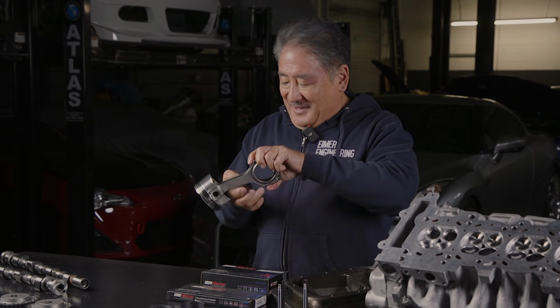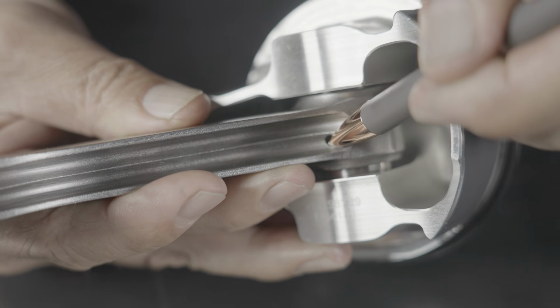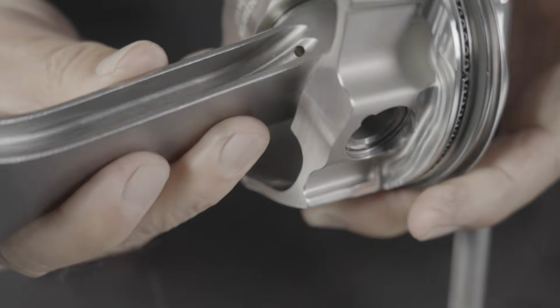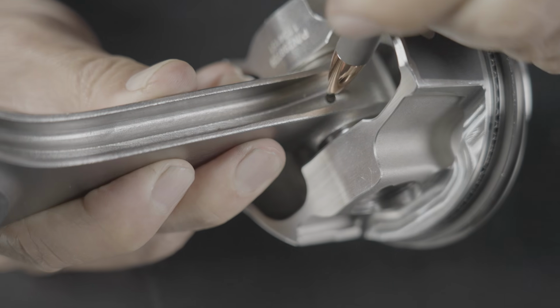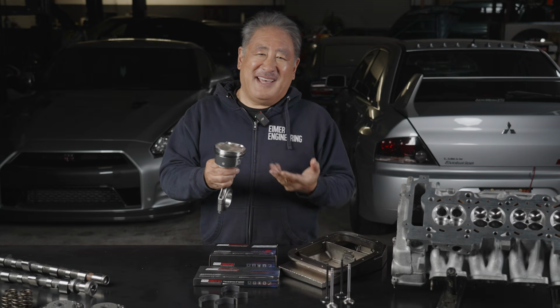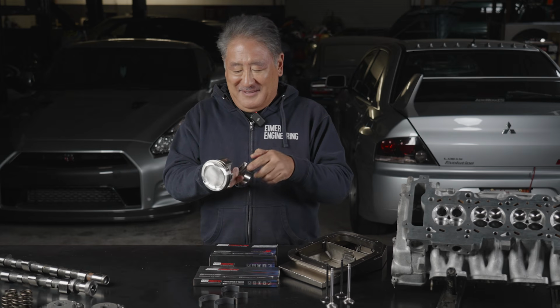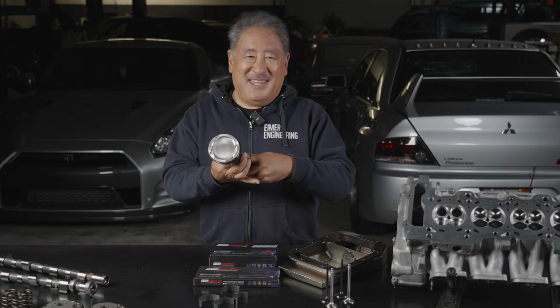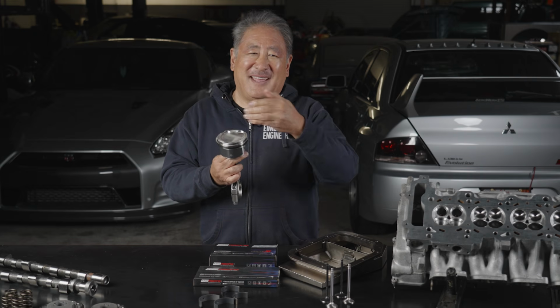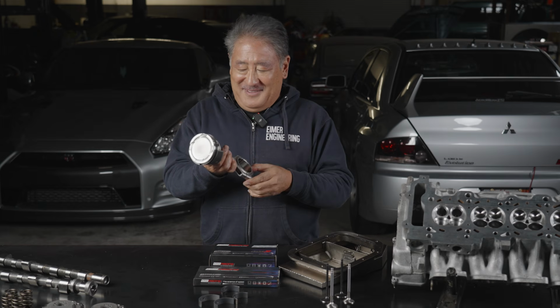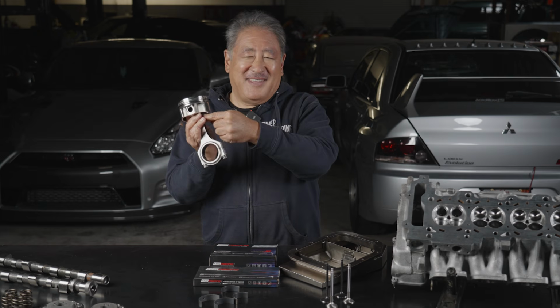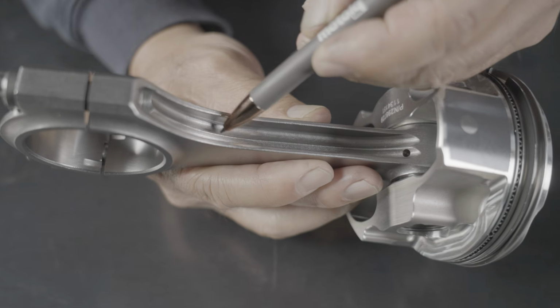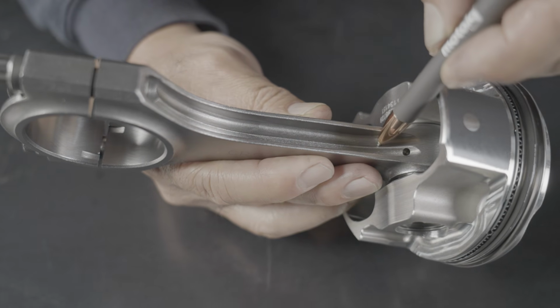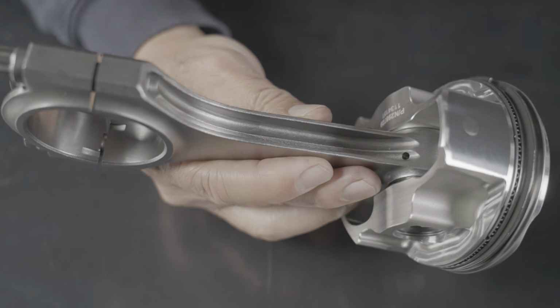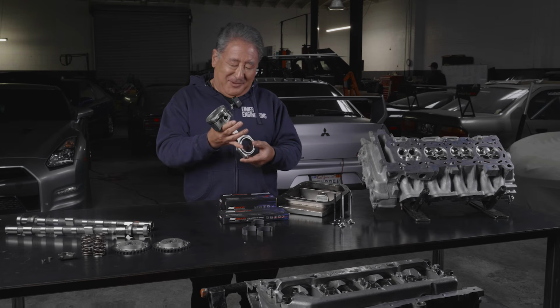There are some other features, like dual pin oiling holes on the underneath of the rod. A lot of rods have the pin oiling hole at the top, but that's also the highest stress part of the rod, and you don't really want a hole there if you can help it. So what Eagle does is put 2 small holes underneath, and that way you don't have that stress place up on top of the piston. I think that's really cool. There's an extra rib down here in the groove. Doing some computer analysis, Eagle found that adding this rib really increased their fatigue strength without adding much weight.